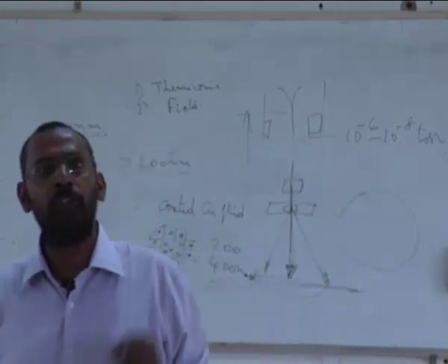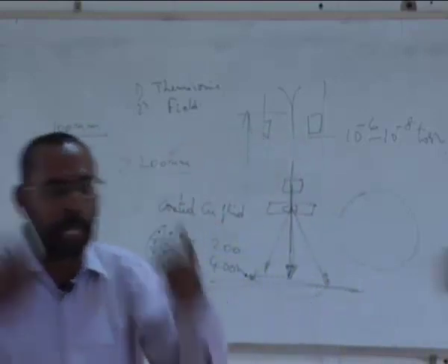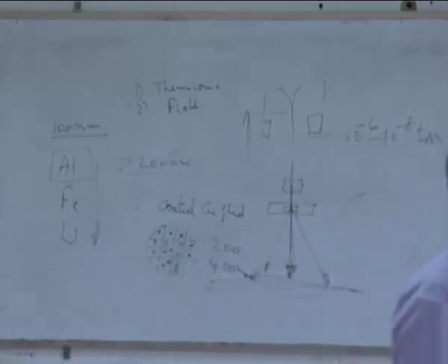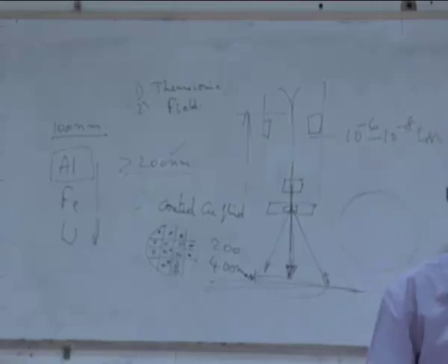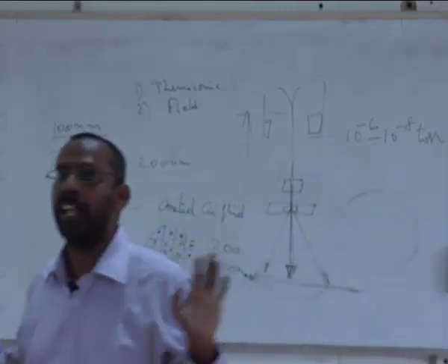And that amorphous carbon also should be very, very thin, so that the electron beam does not get scattered away by the electrons present in that amorphous carbon. Of course, luckily carbon has a very low atomic number, so the scattering will be low because the number of electrons is low. But even there, unless the sheet is very thin, so we use sheets of the order of around 10 angstroms thickness, and such a deposited carbon film is what you put these nanoparticles onto. So this is very easy if you are studying nanoparticles.